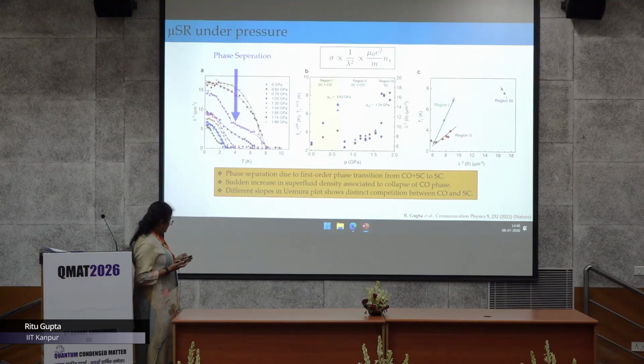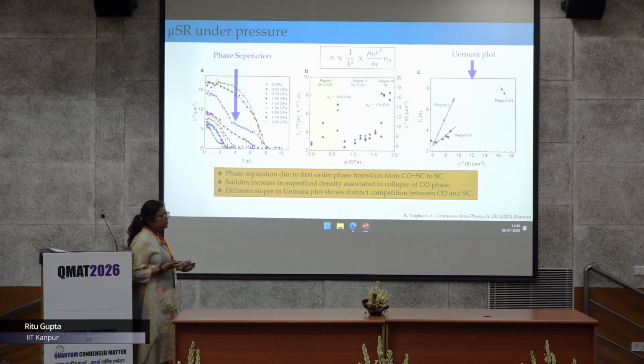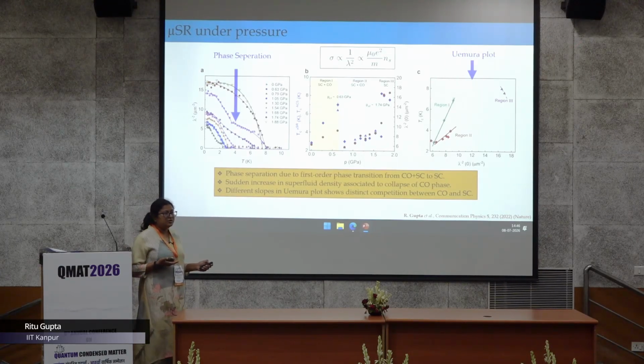If we plot this famous Uemura plot, which is between Tc and superfluid density, in region 1 and region 2 you have two different slopes, and in region 3 of course there is no charge density wave. This is completely suppressed beyond this pressure 1.74 GPa. So in region 1 and region 2, two distinct slopes are telling you that there are two distinct competing natures of charge order phase and superconductivity happening in these regions.